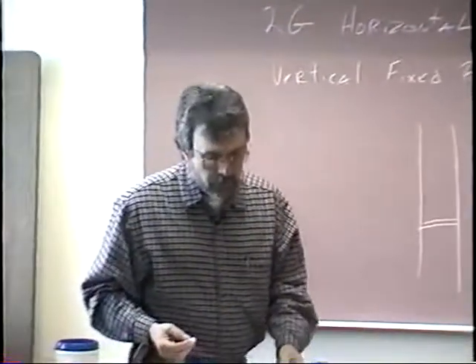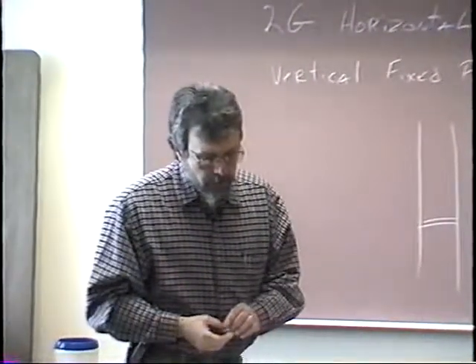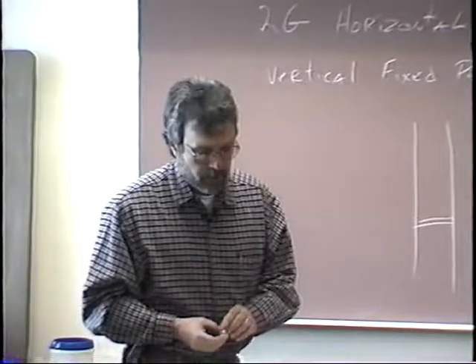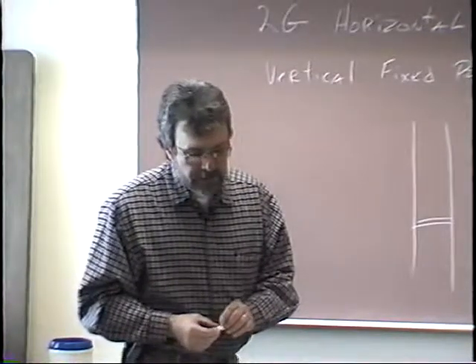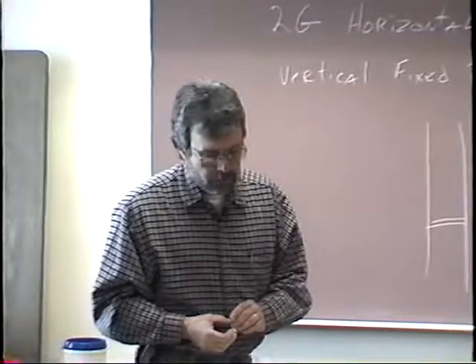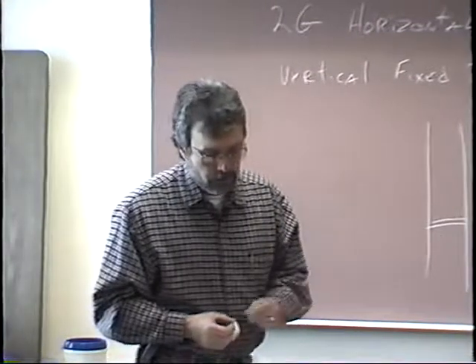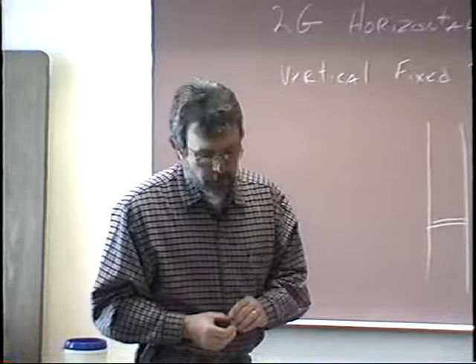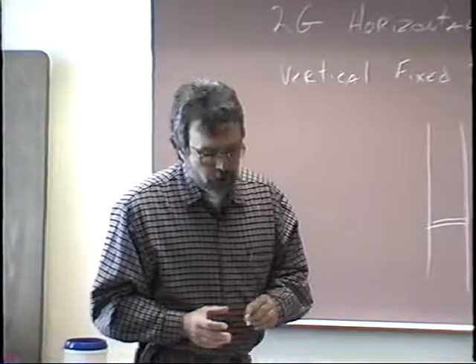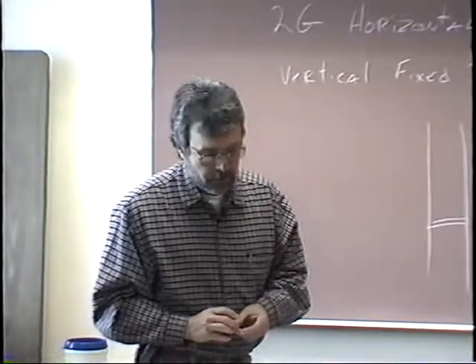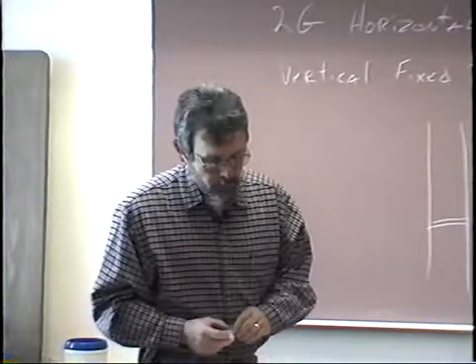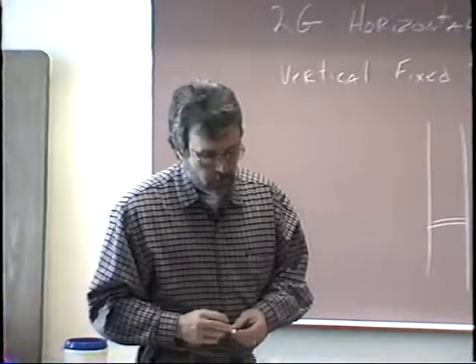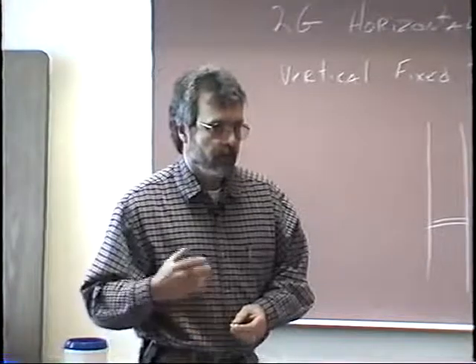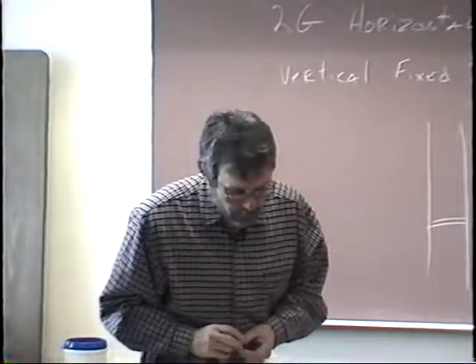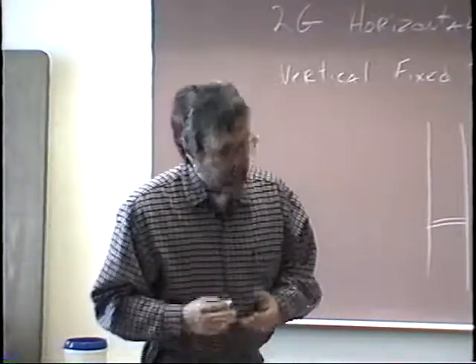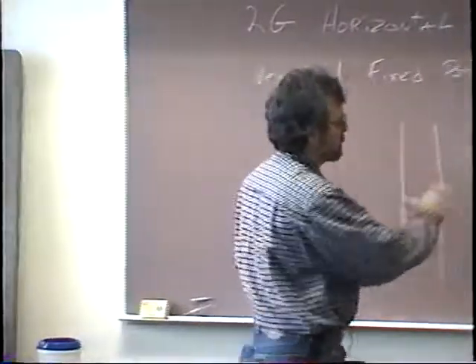If you'll turn the page to 138, top of the page, middle of that first paragraph, it says, usually slightly less current is used when the weld is a horizontal weld in the 2G position than when pipe is in the 5G position. Too much current can cause serious trouble in welding by making the molten metal in the puddle on the upper edge of the weld difficult to control. If you've got too much current, it can cause problems as you're trying to come across here.